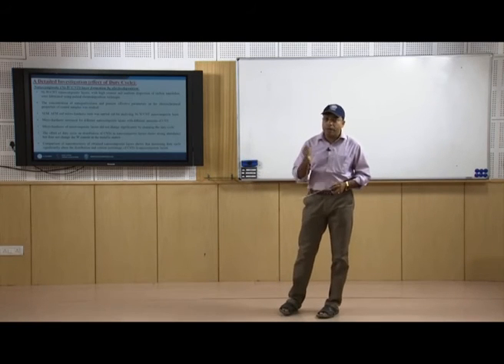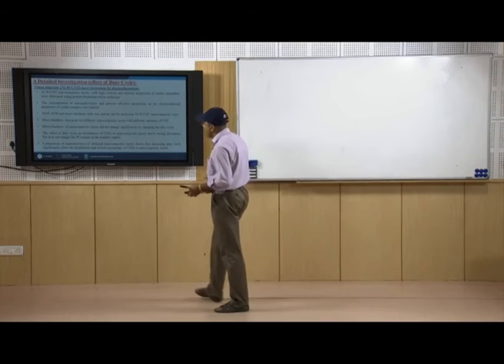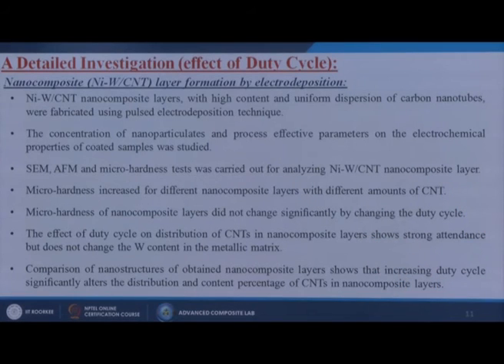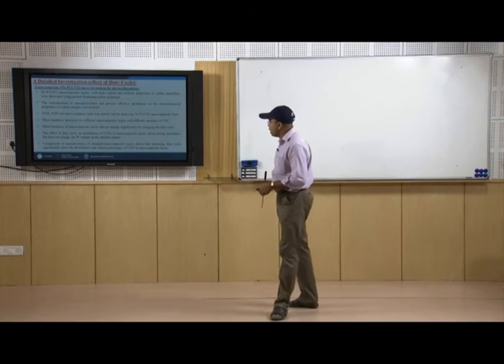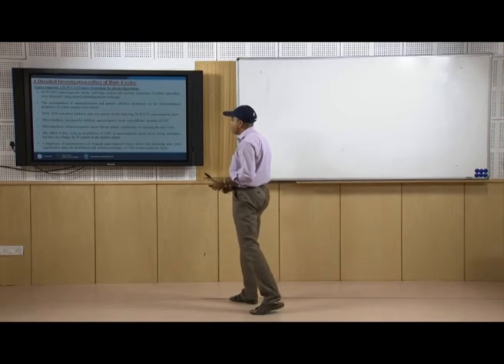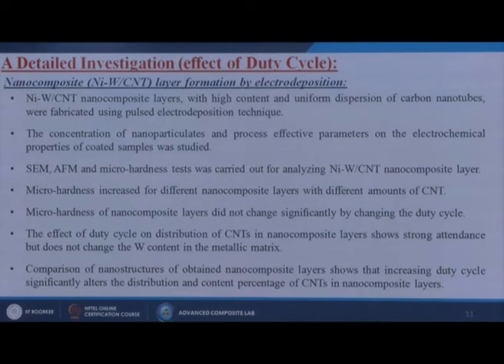That deposition technique we have already discussed in our previous lectures. The concentration of nanoparticulates and the effective process parameters on the electrochemical properties of the coated samples were studied. SEM, AFM and microhardness tests were carried out to analyze the nickel tungsten carbon nanotube nanocomposite layer. Microhardness increased for different nanocomposite layers with different amounts of CNT. So here we are actually changing the loading of the CNT in this composite system. Microhardness of the nanocomposite layers did not change significantly with changing duty cycle. The effect of duty cycle on distribution of CNTs in the nanocomposite layer shows a strong dependence but does not change the tungsten content in the metallic matrix.